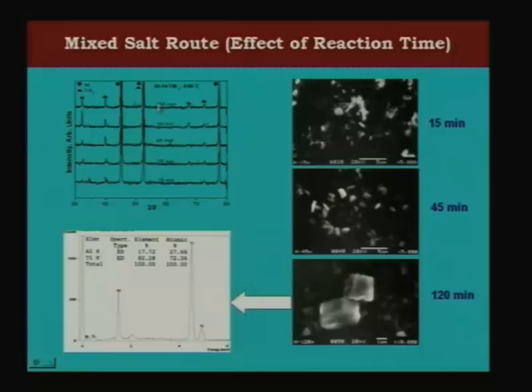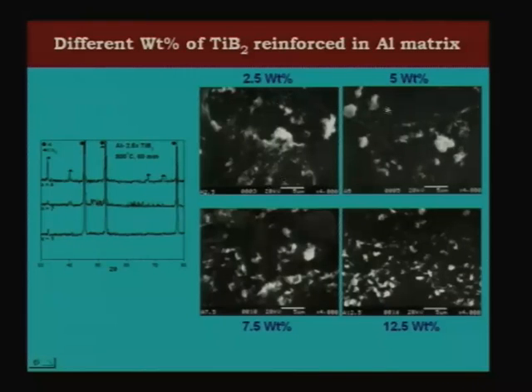And one can also study how the XRD patterns change as you keep on increasing the reaction time, that with increasing reaction time the TiB2 peaks start becoming bigger and bigger. That indicates the volume fraction of the TiB2 is increasing. Okay. So this is again the EDAX to show what is the volume fraction of this is on one of the Al3Ti particles, and one can also vary the percentage of TiB2, the 2.5%, 5%, 7.5% and 12.5% shown here, just to give you an idea that one can vary the volume fraction of these particles so that one can have improvements in the strength. As we know that with higher reinforcement amount we will have better strength.